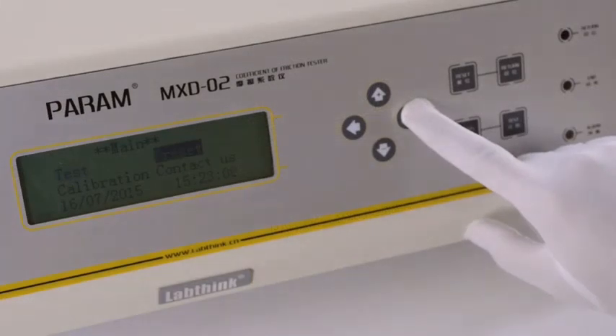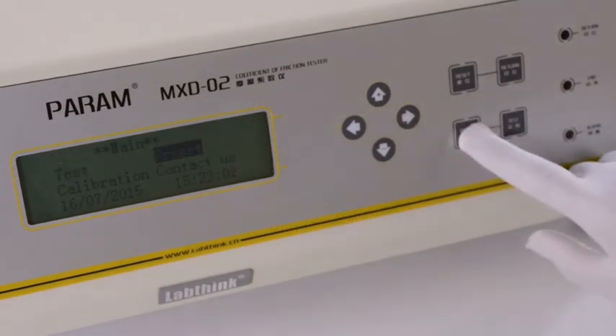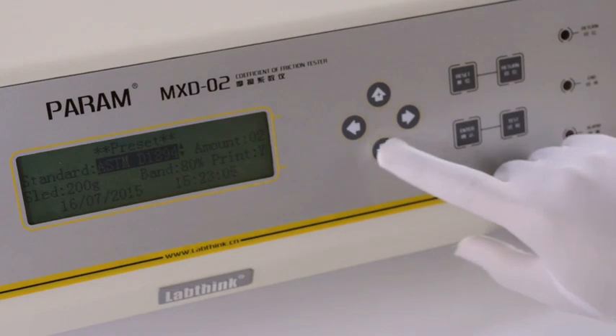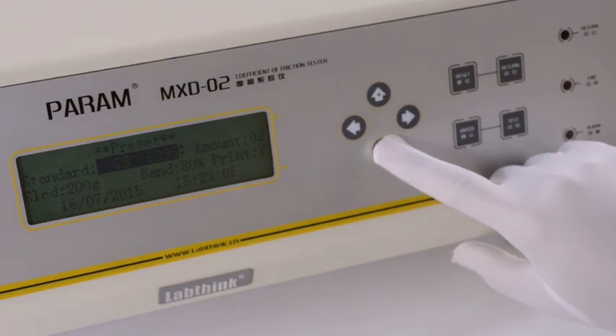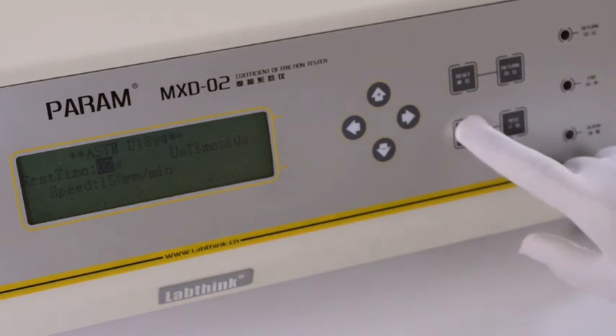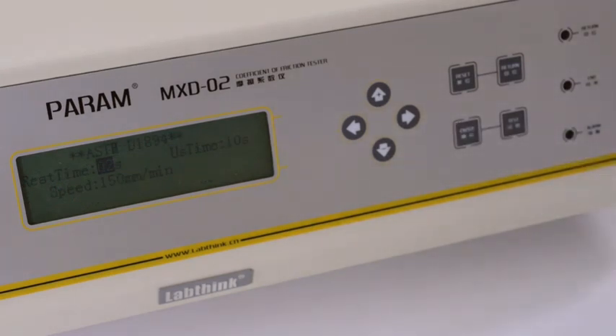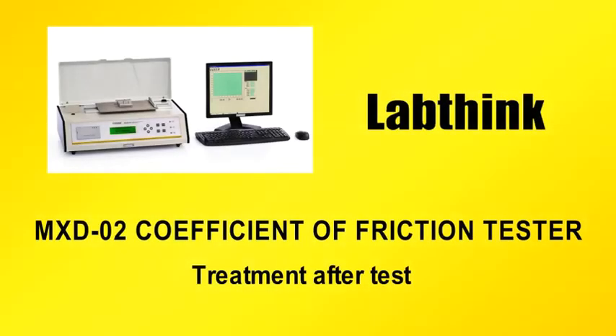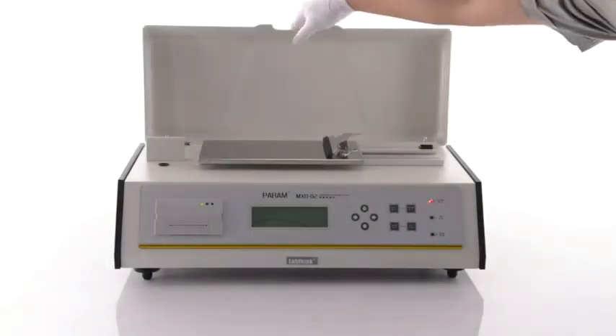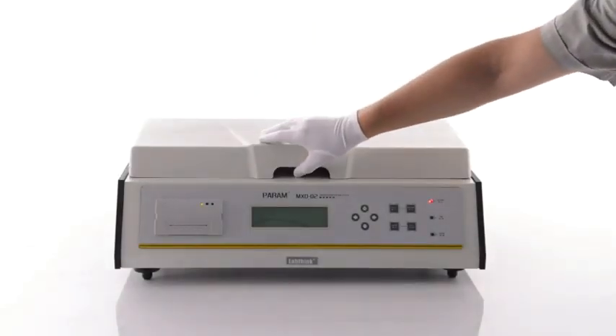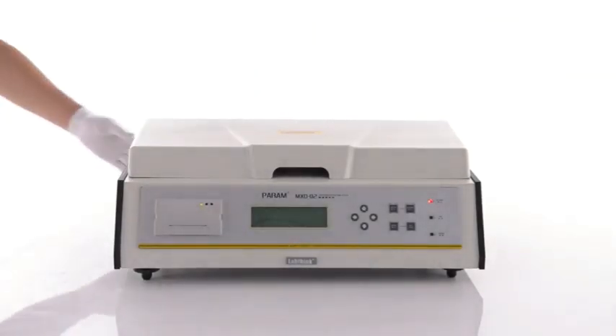Press Enter to enter the preset interface and press left and right arrow keys to move the cursor to standard and select ASTM D1894. The speed will be 150 mm per minute. Treatment after test. Pull down the dustproof cover. Switch off the instrument.